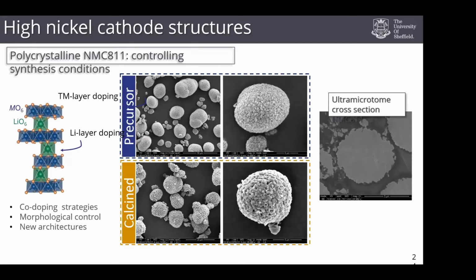We do some neat tricks with the chemistry here, where sometimes we'll replace some lithium and we might put some magnesium in there instead. And the magnesium acts like sort of a stilt or a crutch. It pins these layers in place and doesn't move. And so you end up putting almost like struts into your chemical structure to keep those layers in place.